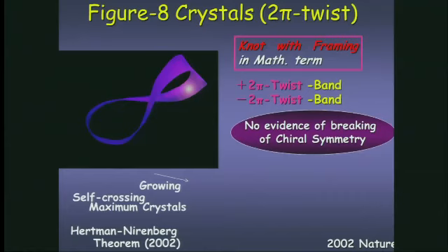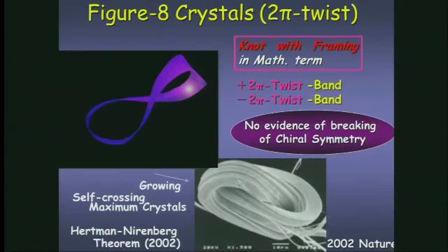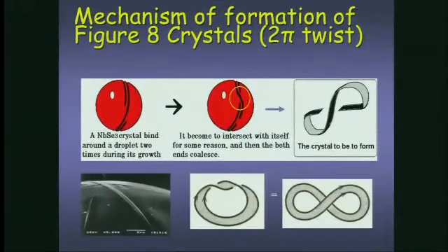There is no evidence of breaking of chiral symmetry. And the figure 8 crystal is a self-crossing Hopf-link-like crystal. The mechanism of formation of the figure 8 crystal is like this figure. The niobium selenium 3 crystal winds around the droplet 2 times during its growth and intersects with itself, and then both ends coalesce. Finally, we obtain this type of figure 8 crystal.